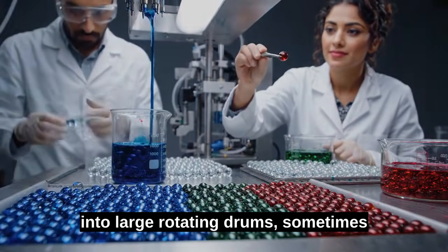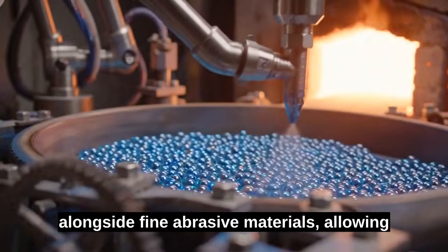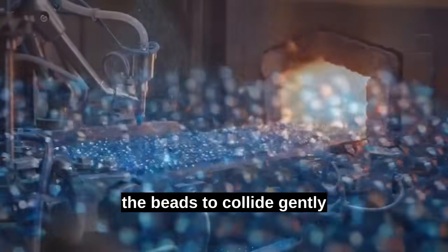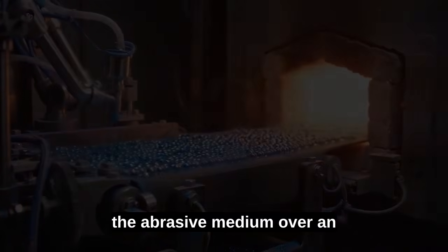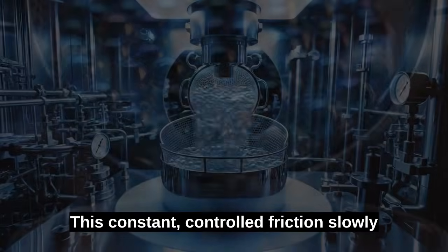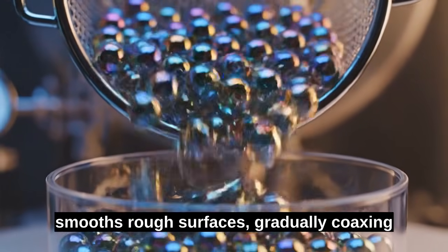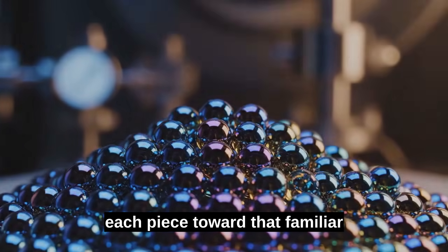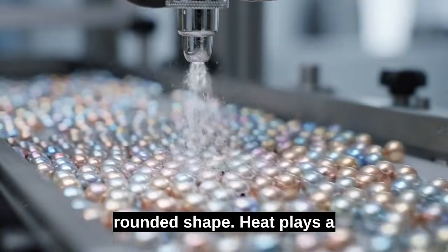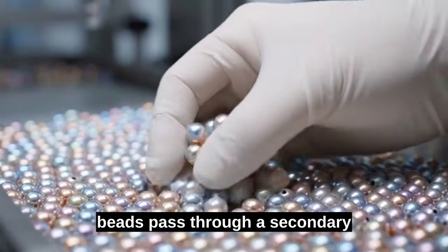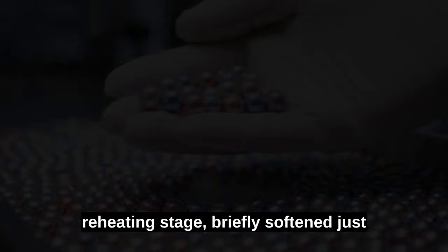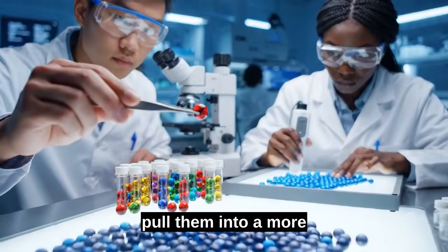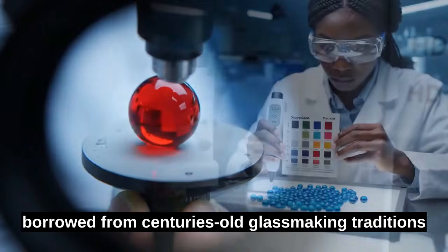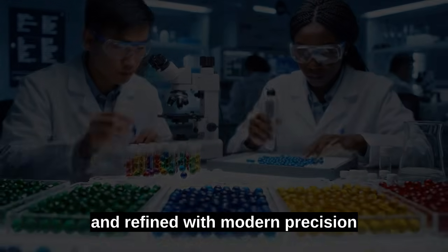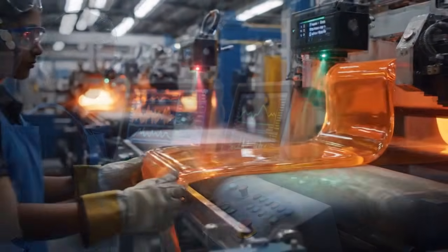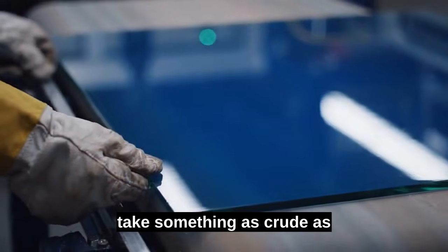To solve this, factories use a secondary tumbling process, loading the rough beads into large rotating drums, sometimes alongside fine abrasive materials, allowing the beads to collide gently with one another and with the abrasive medium over an extended period. This constant, controlled friction slowly wears away sharp corners and smooths rough surfaces, gradually coaxing each piece toward that familiar rounded shape. Heat plays a role here too, because many beads pass through a secondary reheating stage, briefly softened just enough to let surface tension pull them into a more perfectly spherical form, a technique borrowed from centuries-old glassmaking traditions and refined with modern precision equipment.